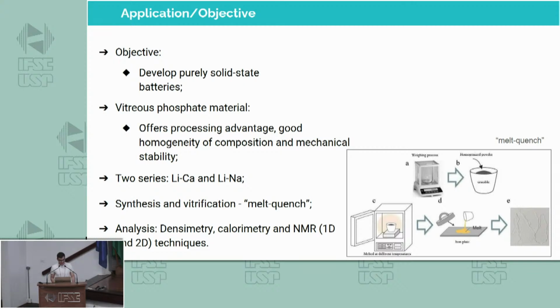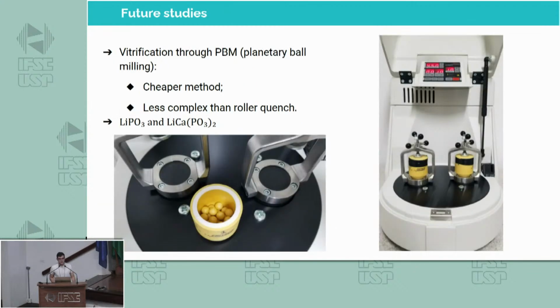We studied 2 series of mixed phosphate glasses with lithium incorporation and 2 other ions, calcium and sodium. We synthesize them in our lab through the melt quench technique and analyze them through densimetry, calorimetry, and NMR techniques. And we are concentrating our study on vitrification through planetary ball milling, which is a cheaper and less complex method than roller quench, the usual method that we use.